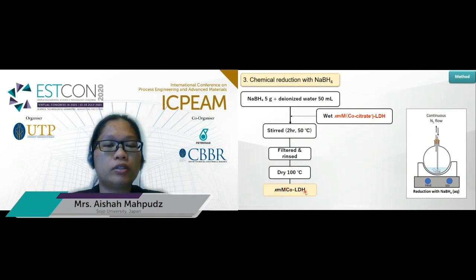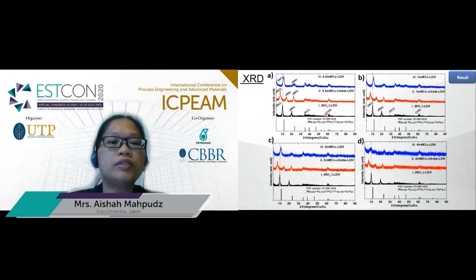cobalt citrate solution. So this is the X-ray diffraction pattern of the set of samples synthesized from 0.5, 1, 2, and 4 millimolar cobalt citrate solution. The black X-ray diffraction pattern refers to the nitrate LDH, the red line refers to the XRD after anion exchange, and the blue line represents the diffraction pattern of the sample after reduction with sodium borohydride. So in all these four samples, a similar trend of shift in the basal peak 003 can be observed.